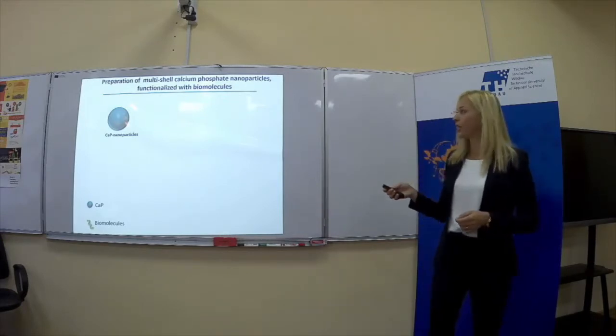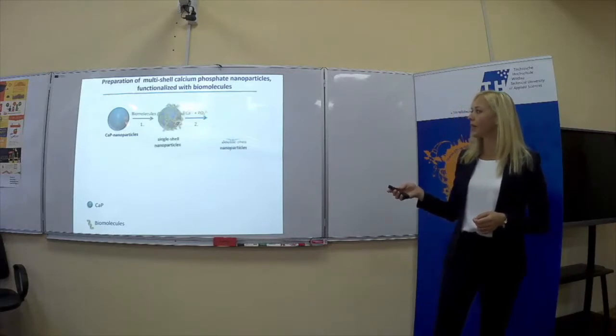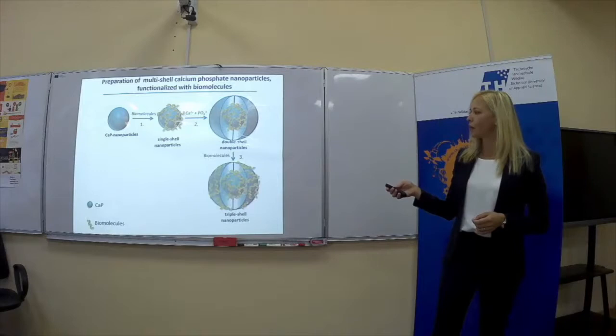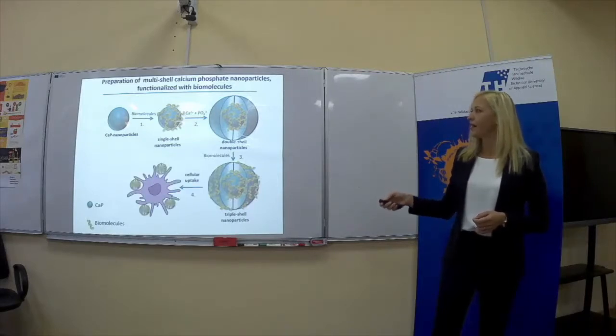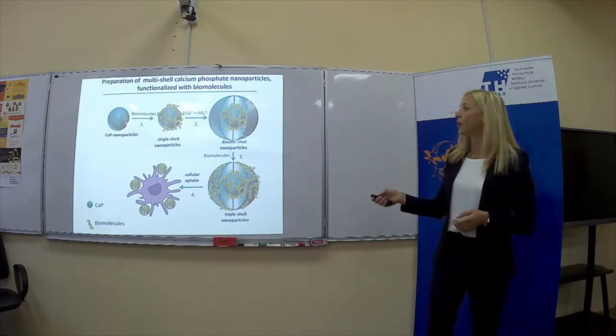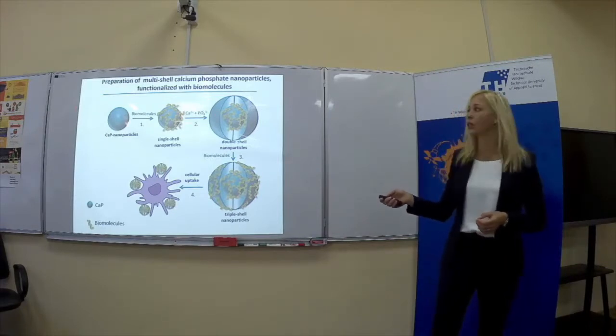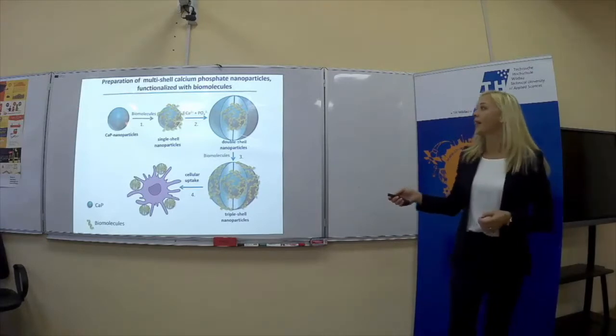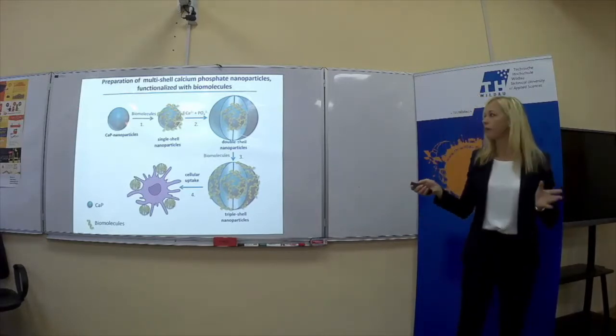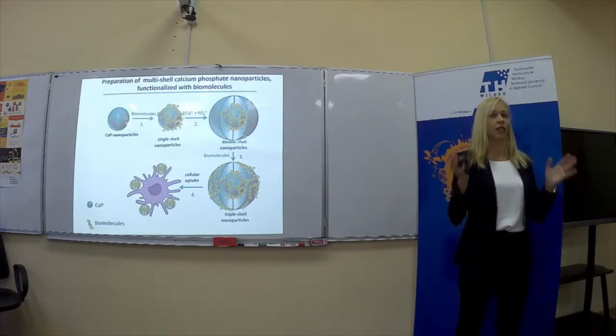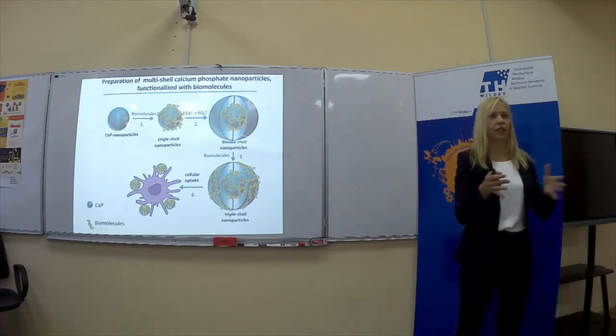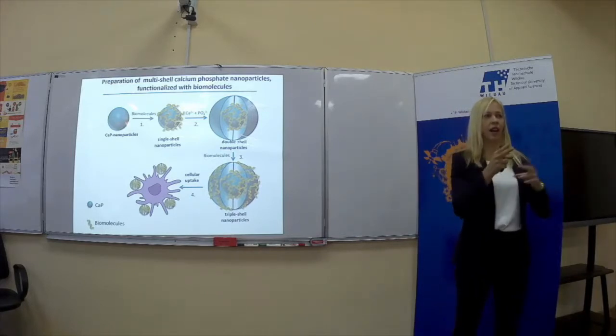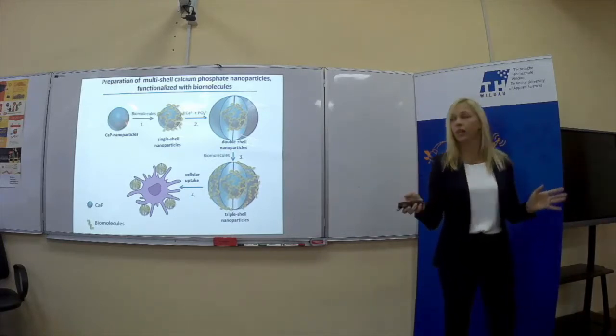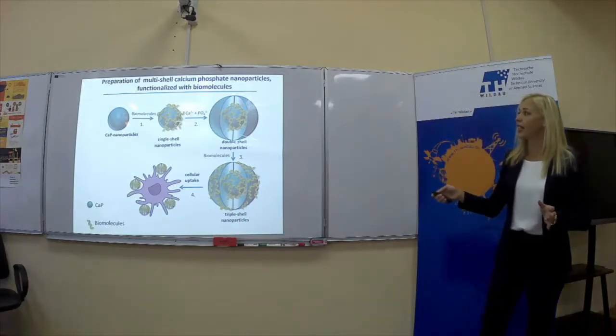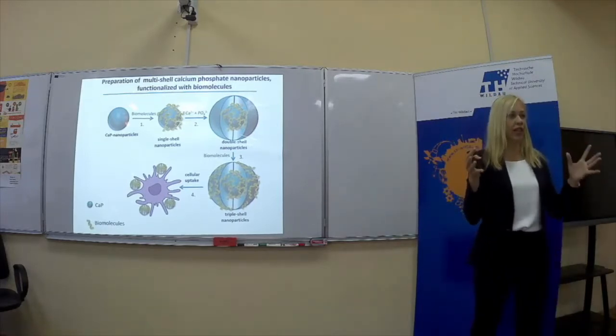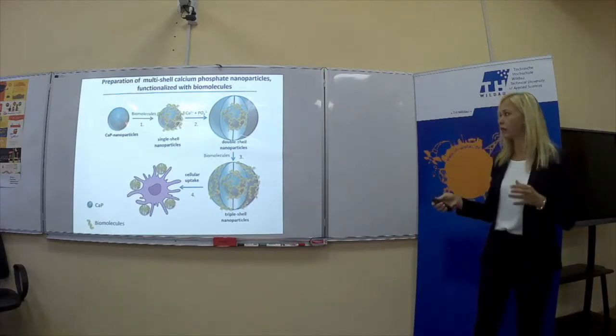In my PhD work, I was working and establishing such kind of nanoparticles. I will put everything together, and here you can see we have calcium phosphate, like I showed you. After you add DNA, for example, on the surface, you stabilize nanoparticles, but these biomolecules are not protected. Imagine, such nanoparticles go inside of the cells, and there are so many enzymes, they just cut biomolecules, and they are not active anymore. For this idea, we decided to prepare one more shell to protect biomolecules from degradation.